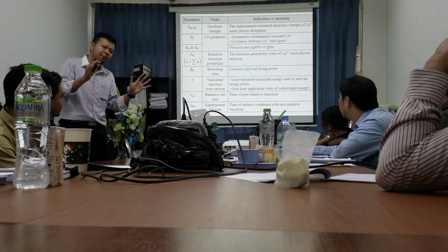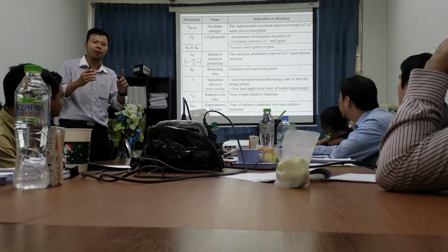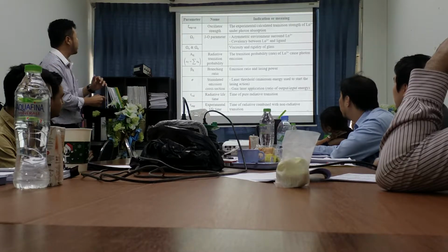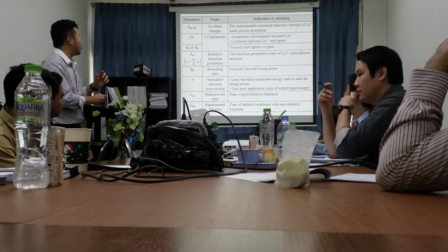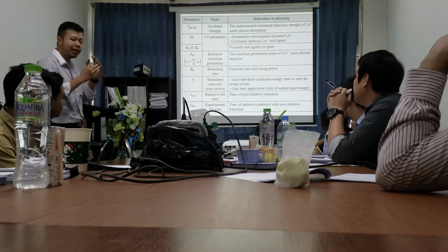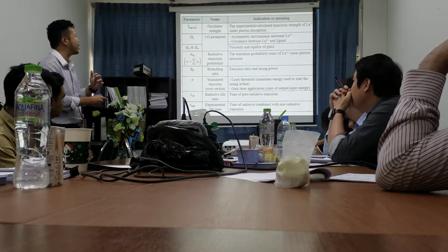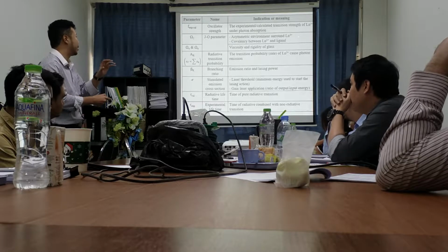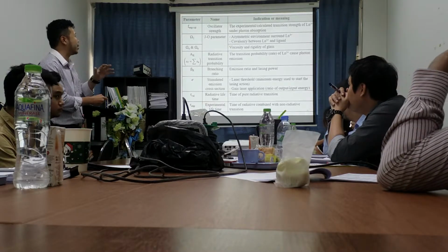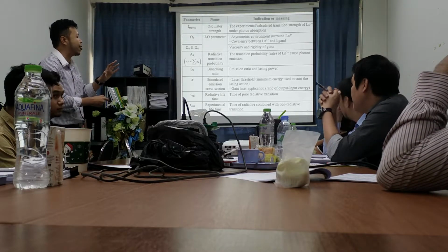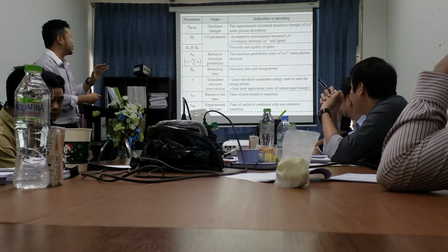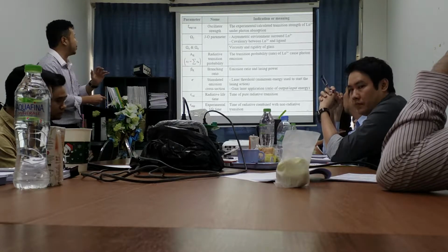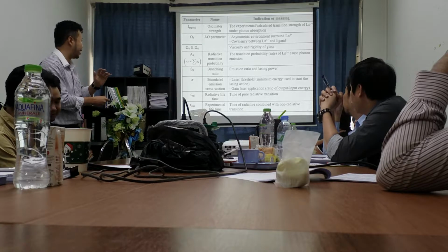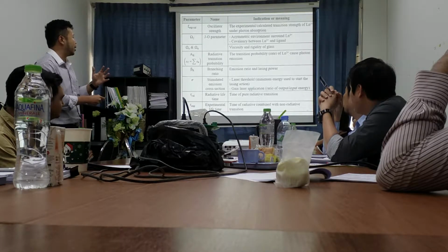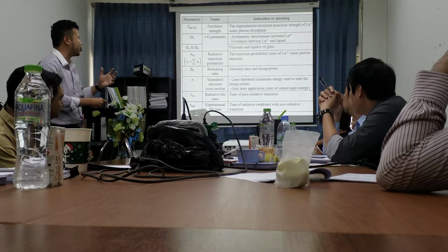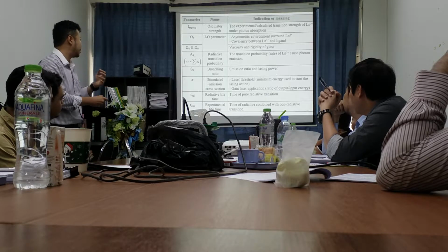Because we have many parameters in my thesis, I just talk about the important ones. Okay, just start with Omega 2. Omega 2 tells us about the degree of asymmetry of the environment around the lanthanide ions in the glass matrix. And it can also tell us about the degree of covalency between the lanthanide ion and ligand. Omega 4 and 6 tell us about the degree of viscosity and rigidity of the glass. Branching ratio shows the emission ratio and lasing power from this glass.